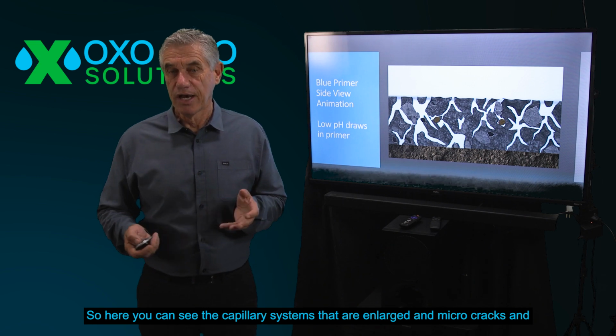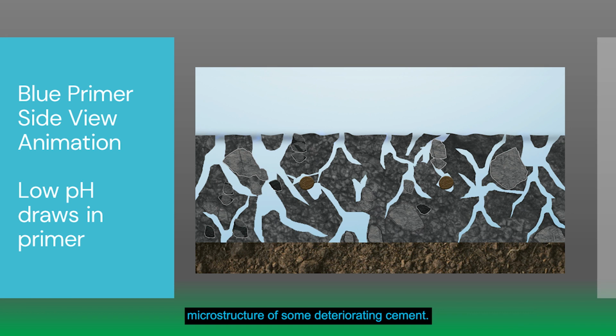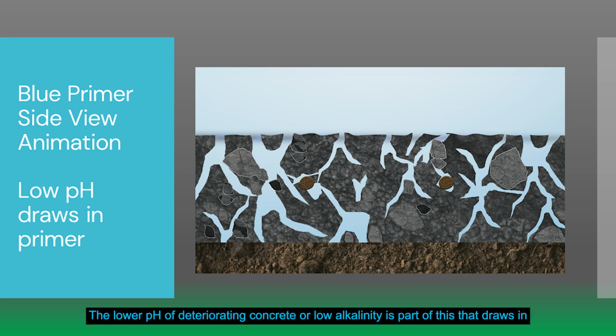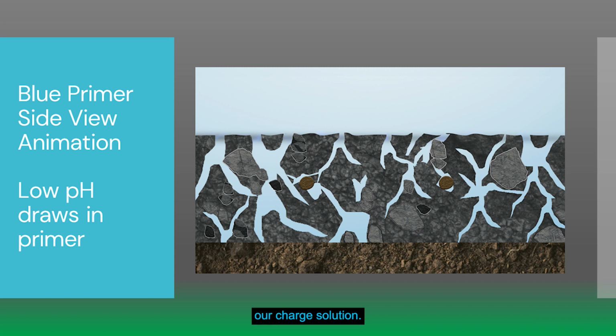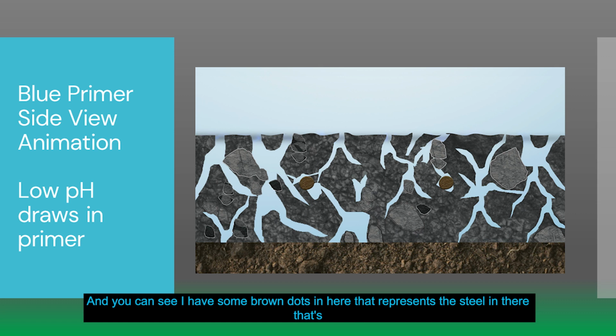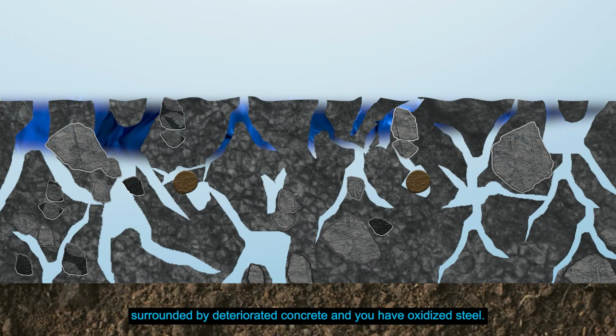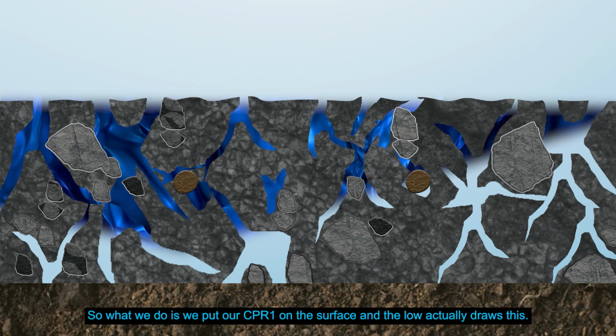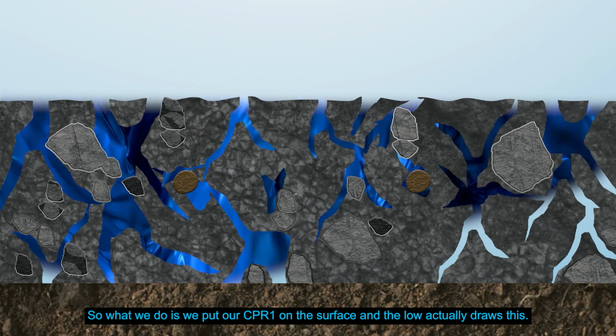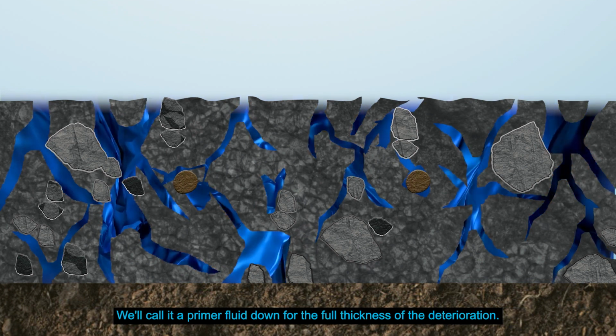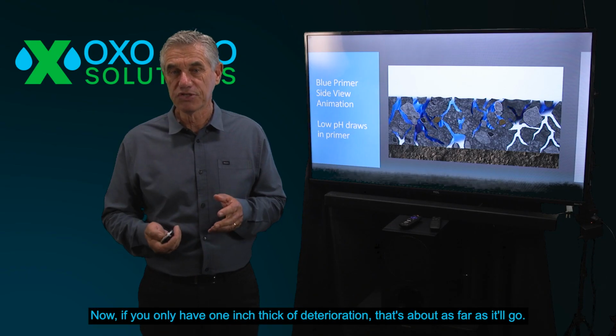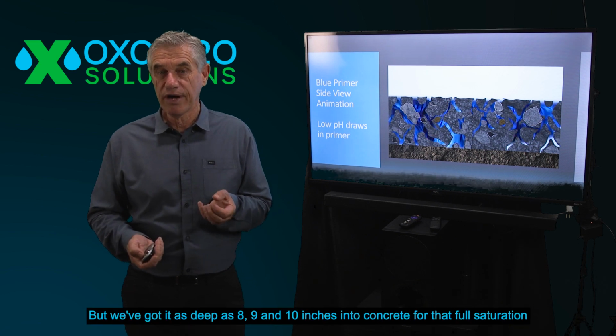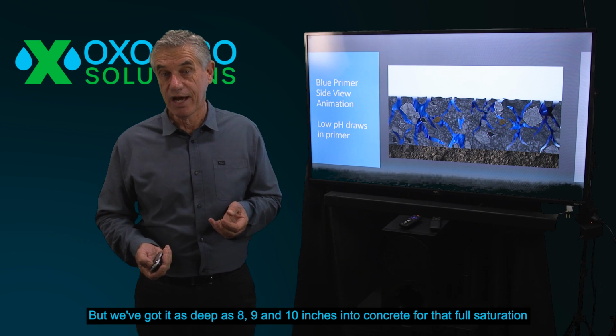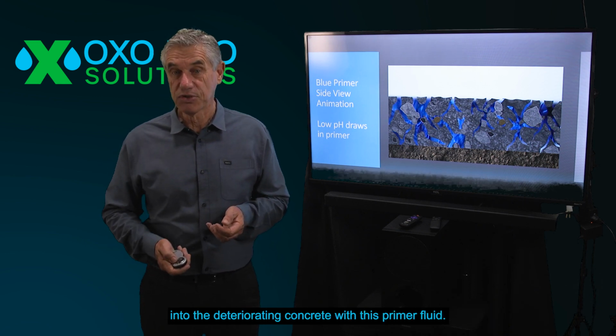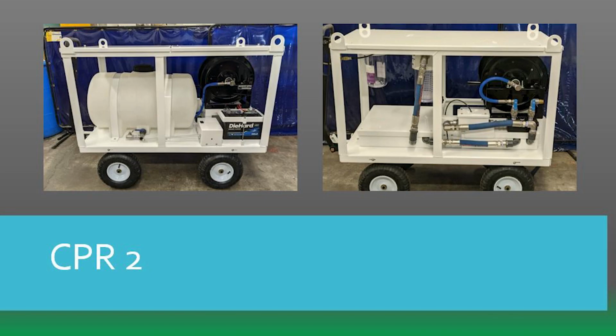So here you can see the capillary systems that are enlarged and micro cracks and microstructure of some deteriorating cement. The lower pH of deteriorating concrete or low alkalinity is part of this that draws in our charged solution. And you can see I have some brown dots in here that represents the steel in there, and that's surrounded by deteriorated concrete, and you have oxidized steel. So what we do is we put our CPR1 on the surface, and the low pH actually draws this, we'll call it a primer fluid, down for the full thickness of the deterioration. Now, if you only have 1 inch thick of deterioration, that's about as far as it'll go. But we've got it as deep as 8, 9, and 10 inches into concrete for that full saturation into the deteriorating concrete with this primer fluid.